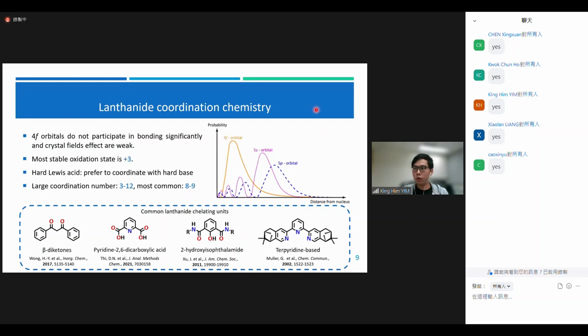So you learn about crystal field, you learn about ligand field. So you know when the transition metal coordinates with the ligand, the ligand field will split the d orbitals into Eg and T2g, right? But for lanthanide, the orbital energy level will not be affected that much by the ligand, because the 4f orbital is well shielded, well protected by the 5s and 5p orbitals.